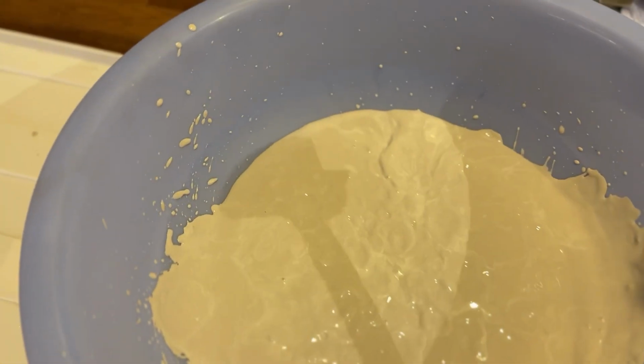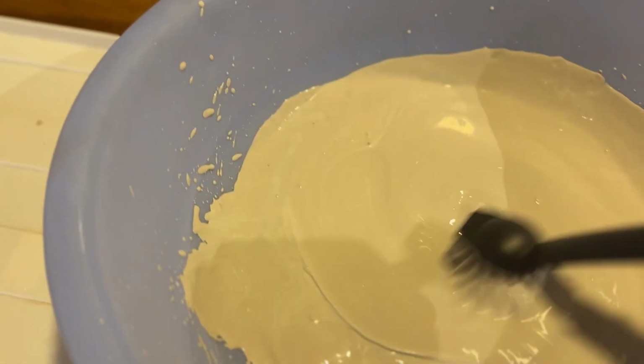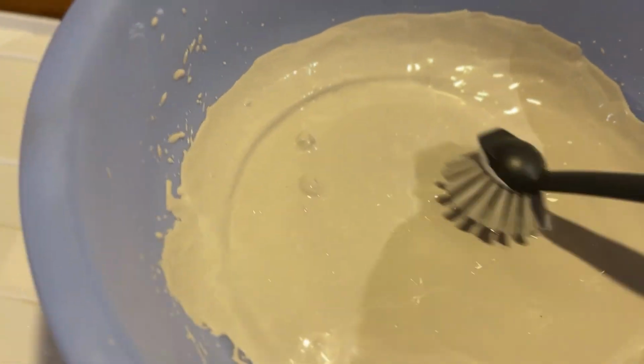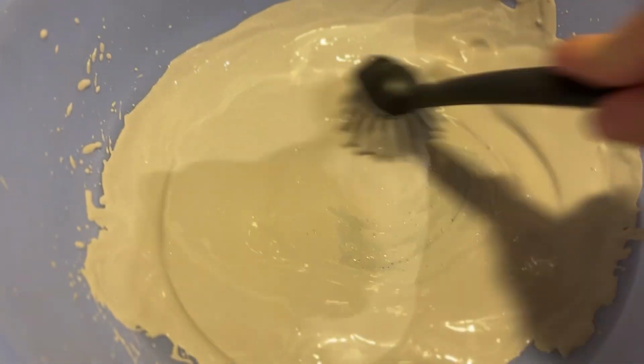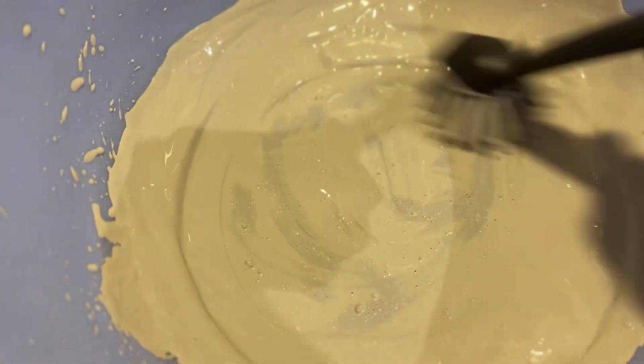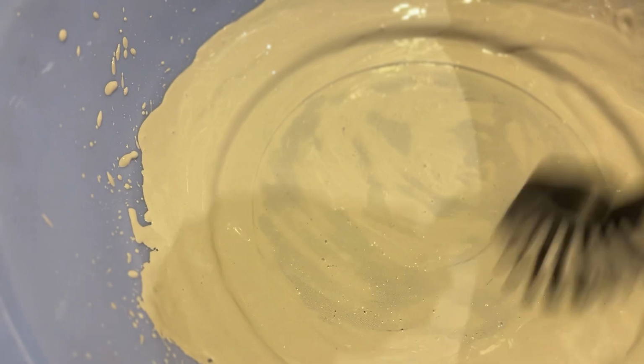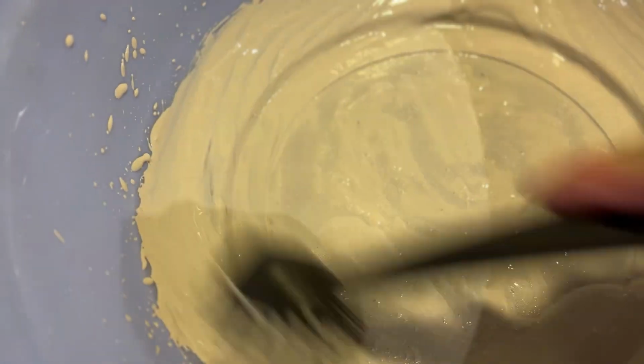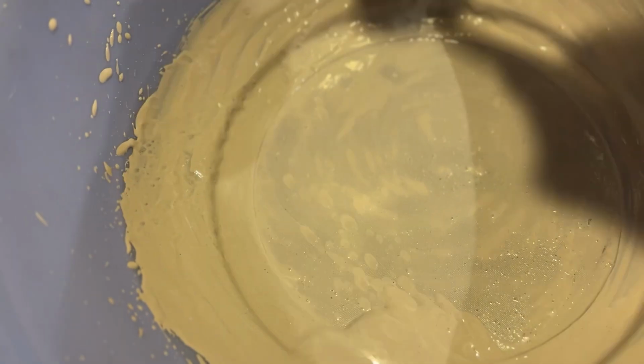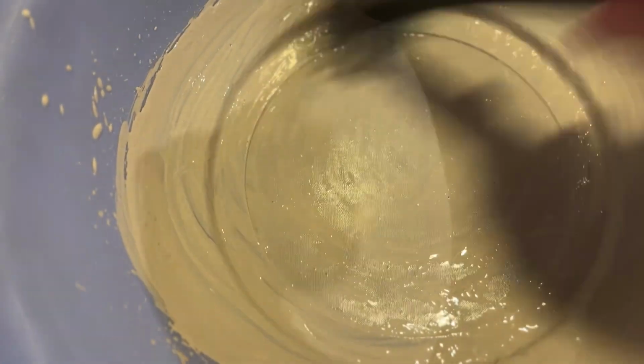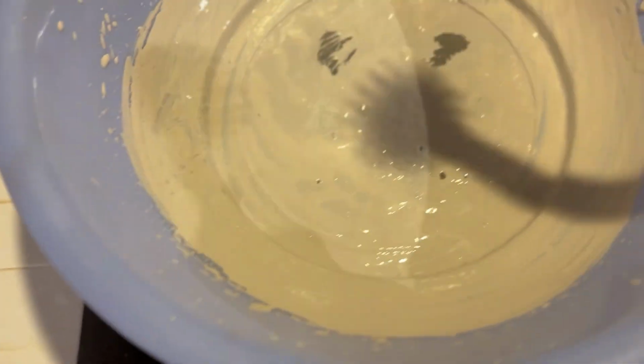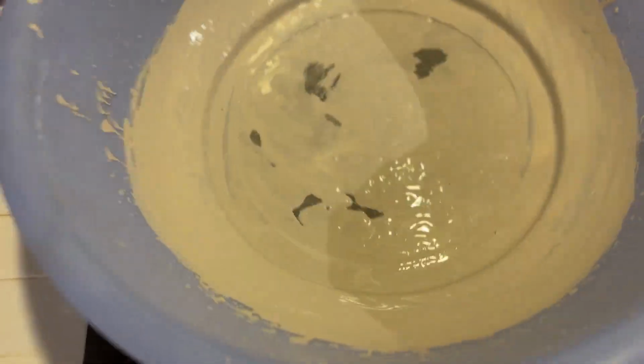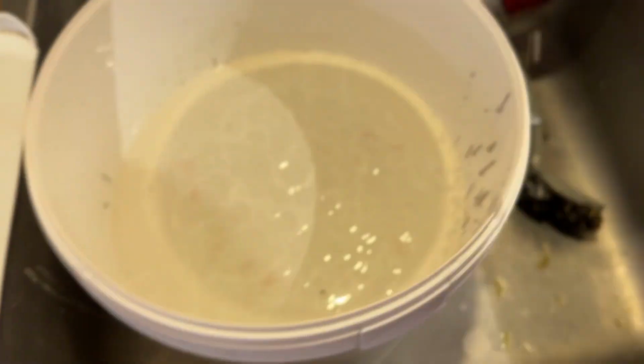So this one was actually mixed pretty well. Most of it just went through, but as you can see, there's something left here, and that's the drier part of it. And just by using this brush, it was a little bit difficult when I have to hold the camera too, but I think you get the point. You can actually push it through and make sure that everything that goes into this bucket is no bigger than the mesh in the sieve. I think this is good enough. I usually just tap it a few times to make sure that there's not too much hiding underneath.